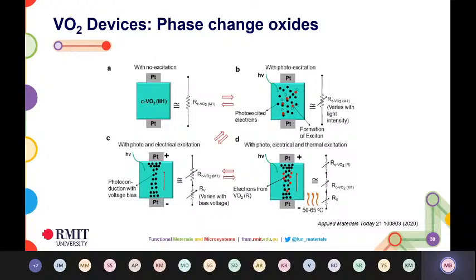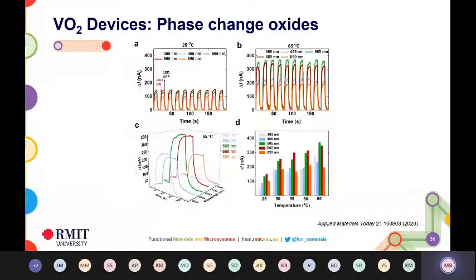Some of our recent work in this case was when we tried applying different stimuli on the material to try and understand how the photoresponse of the material actually changes once you apply 3 different kinds of stimuli. This shows you the mechanism of what happens where you have deep level, where you create some intermediate states, and that affects its photoresponse generation occurring at different wavelengths. You can see in this particular case, we measured the photoresponse across different wavelengths at room temperature, which changes significantly once you heat up the material to 65 degrees centigrade. 65 degrees centigrade is when it's actually transforming from being an insulator to a conductor. So it starts behaving very differently once you heat up the material.